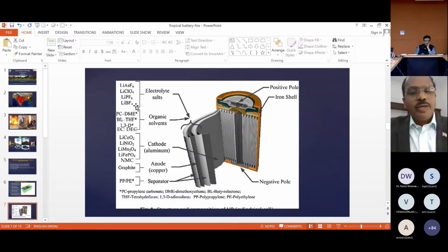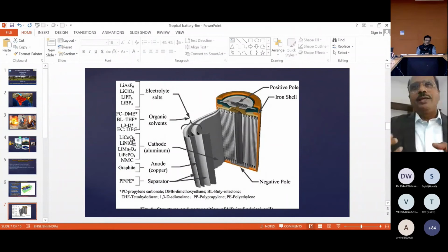In addition, you have the electrolyte salt, essentially LiPF6, a fluorinated salt, and when the electrolyte decomposes, you also get fluorocarbons or even hydrogen fluoride. And you have the cathodes, which are the most dangerous part, because they initiate the reactions for the blowing to happen. Lithium cobalt oxide, lithium nickel oxide, and nickel manganese cobalt are all layered oxides by structure, solid state structure, and they easily give up oxygen when the temperature shoots to around 300 or so. That means as the temperature keeps increasing, the cathode decomposes and gives off oxygen, which catalyzes the burning, and then it blows up. That's the reason NMC, especially with cobalt, likes to give the oxygen away.